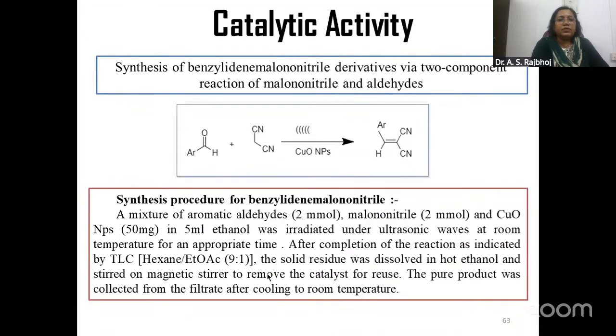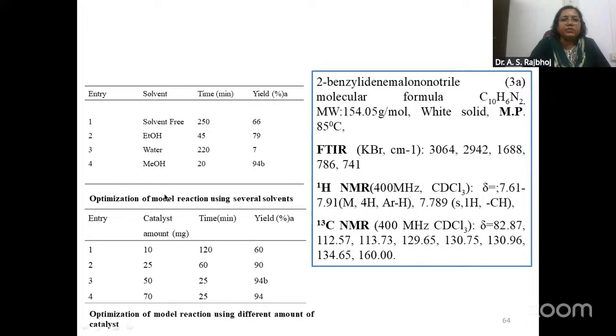Then we have also done a catalytic study, that is synthesis of benzylidene malononitrile derivatives via a 2-component reaction of malononitrile and aldehydes. You can see here malononitrile and aromatic aldehydes have been used, and copper oxide nanomaterials have been used in 5 ml ethanol, and this study has been done by the ultrasonic method at room temperature. The reaction time required was very less. You can see the time required by using our catalyst.